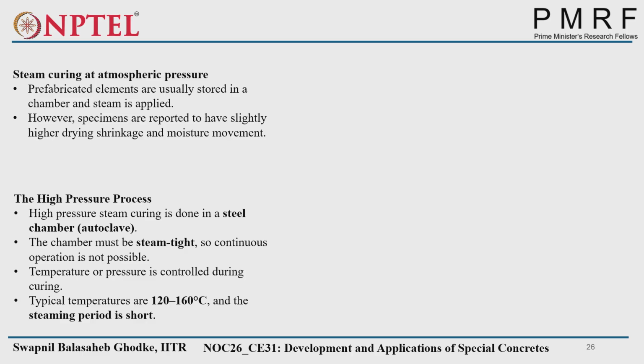But in the case of the high pressure process, an autoclave is used. It is a closed steel chamber and the chamber must be steam tight. So continuous operation is not possible. Continuous operation means we keep a specimen in the autoclave and the autoclave stays closed until curing is complete. We cannot put another concrete specimen in, so that is a discontinuous process. Temperature and pressure are controlled during curing. The temperature in the high pressure process is always between 120 to 160 degrees Celsius, and the steaming period is short.